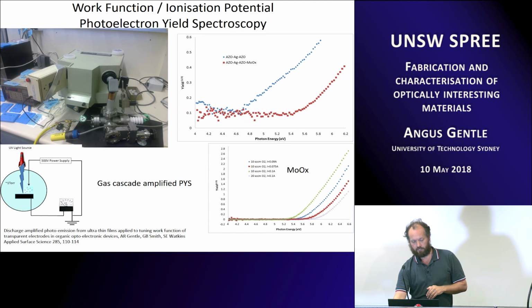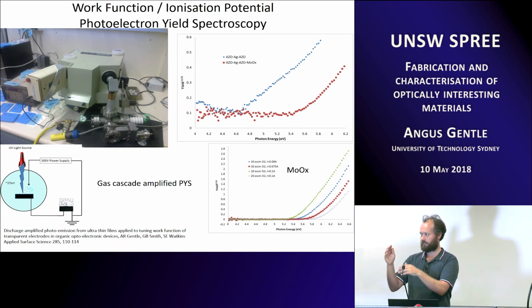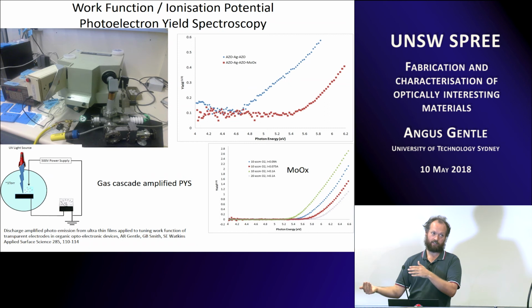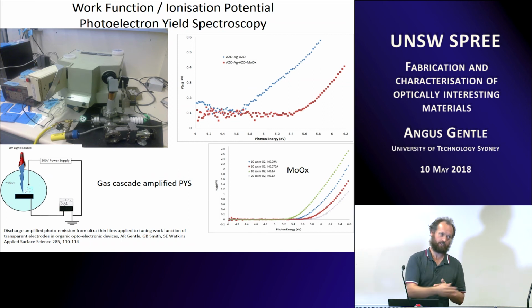So you can take that data and then compare it to the PESA instrument, which is the commercial instrument you can get. And we also did comparisons with UPS, and often you'd find that the measurements from this or PESA would be more relevant for when making a device than if you used UPS, just because once it goes into UPS, you put it under a vacuum, and moly oxide, for example, the oxidation state changes, and then your work function shifts, and you no longer have it working properly.